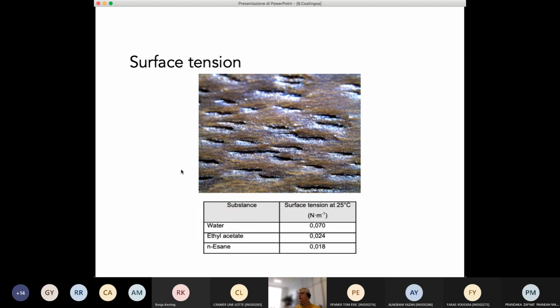The surface tension, we already know what the surface tension is. For water, it is higher than the surface tension of other organic solvents. So this surface tension prevents water from entering inside the porosities of wood, and the final effect can be a surface like this. It looks like the surface of the moon, simply because, as I said, water, because of the high internal cohesion, doesn't easily fall inside the wood porosity.